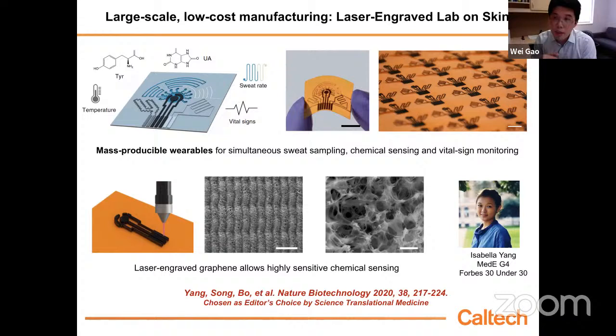If you control the parameters properly, the graphene structure, the property and morphology, can be tuned by laser cutting parameters. Based on this, we can design high performance graphene with very good electrocatalytic activity for high performance chemical sensing. Certain graphene structures can also be used for high performance physical sensing. And we can also use CO2 laser cutting to make microfluidics. Why do we need the microfluidics? Think about that. We are sampling or detecting sweat. When new sweat comes out, it will push away old sweat, right? In this case, you avoid the mixing between new sweat and old sweat.